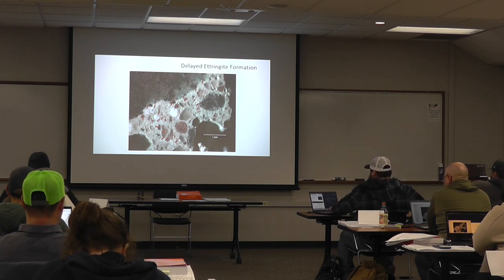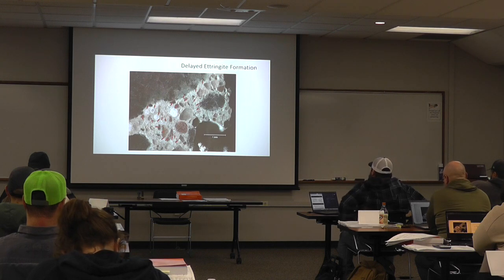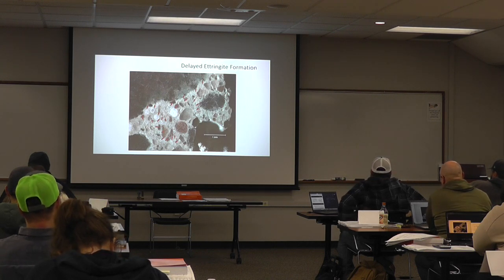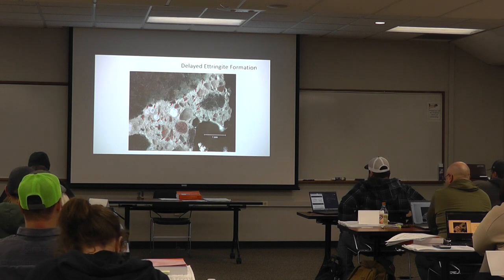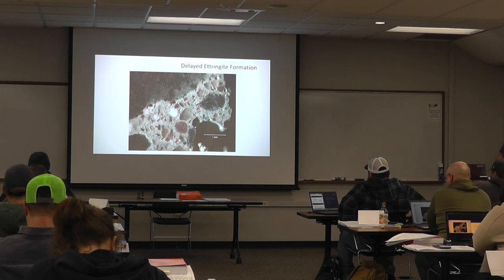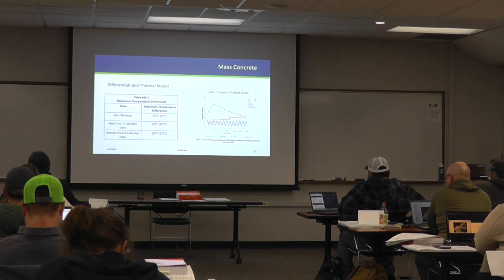And so that's why we have a max temperature for mass concrete too. If our concrete gets above 160 degrees, then the ettringite is going to stop forming, but it will form later, and you don't know when it will. It's really hard to forecast when that ettringite will start forming. So the best way to handle it is to allow it to form during the hydration reaction anyway. That's why we have a max peak for mass concrete.